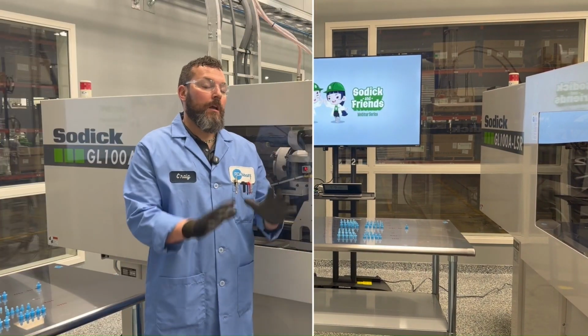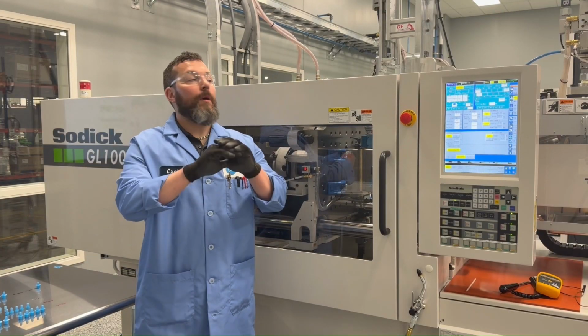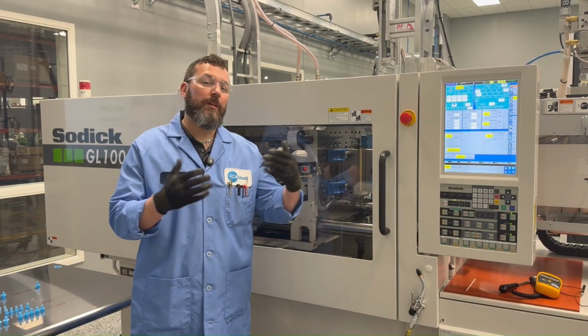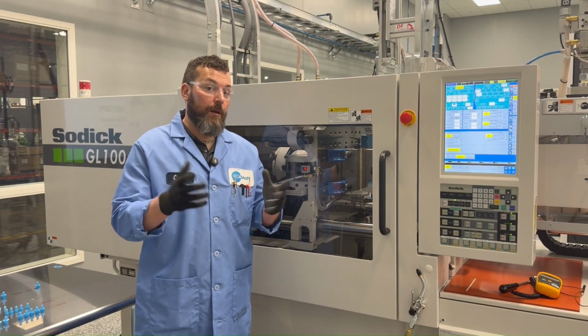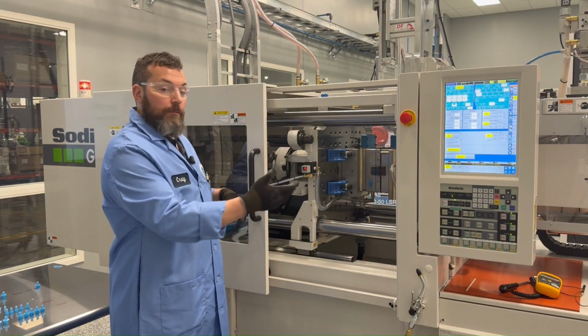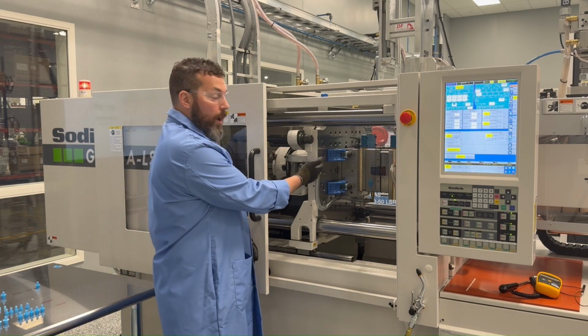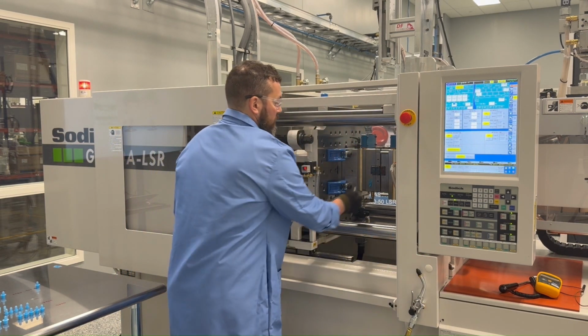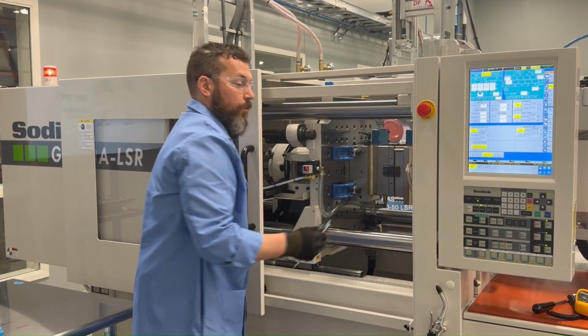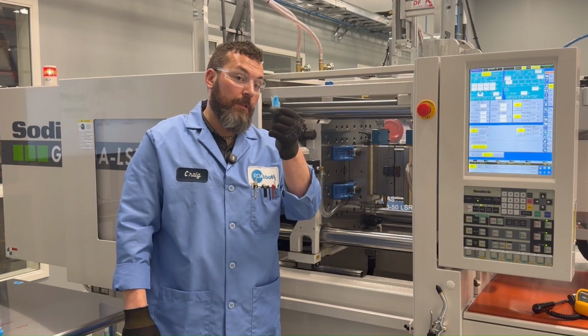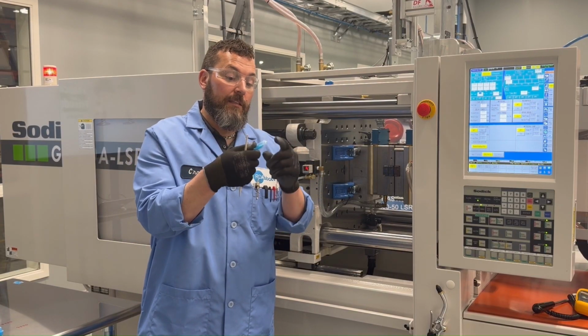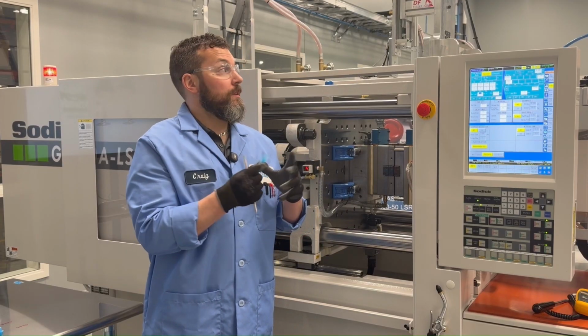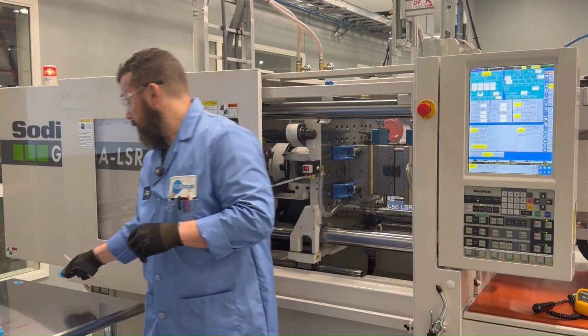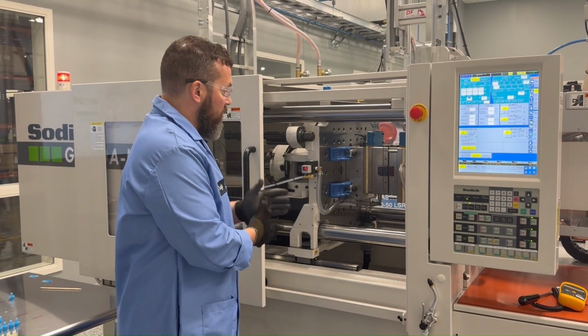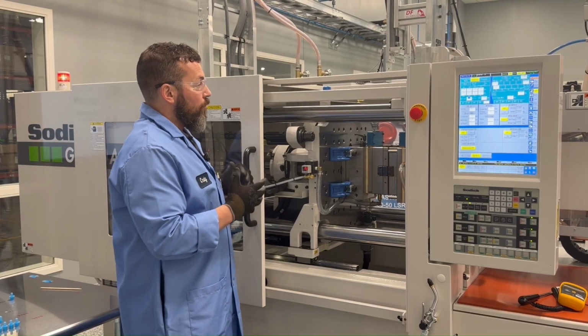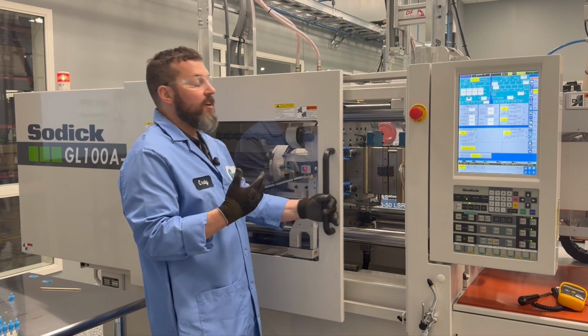Most important part with starting up before you do anything, run rheology on the material. See what the cure kinetics are. If you don't have a system, the easiest way, purge some material out of your machine nozzle and wipe it on the tool. We don't need a lot, but we're just checking to make sure that that material is cross-linking. If this is still wet and it does not cure, we've got ratio issues, and we're gonna have to look into that. So as we're starting, again, I will start with no vacuum to start off. Just want to see how this is filling and the reaction of the system itself.